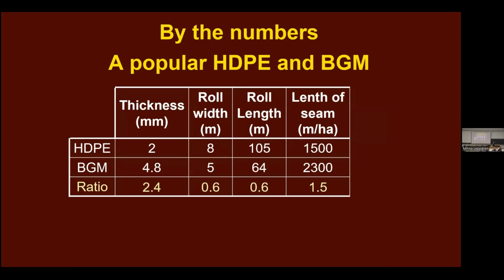HDPE, 2 millimetres thick, BGM, 4.8 millimetres thick. BGM is certainly a lot thicker. The roll width for HDPE is 8 metres, BGM is 5. The length of the roll, 105 and 64. What does that all mean? More welds. So in 1 hectare, we have 1,500 metres of weld in the HDPE, and 2,300 metres, or 50% more, for the BGM. So 50% more susceptible to failure.